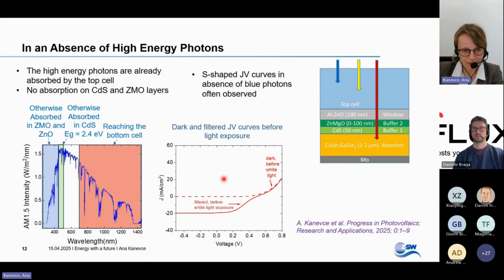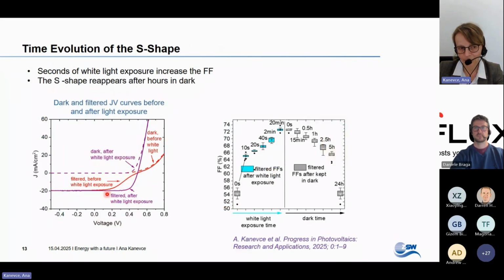On second glance, there is this issue which has been observed many times. This is when a CIGS cell is illuminated only with low energy photons, so with photons with energy below 2.4 electron volts. A lot of cells have a tendency to show an S-shaped curve. This is also known as a red kink, and is manifested with very big fill factor losses. After illumination with white light, this kink disappears.